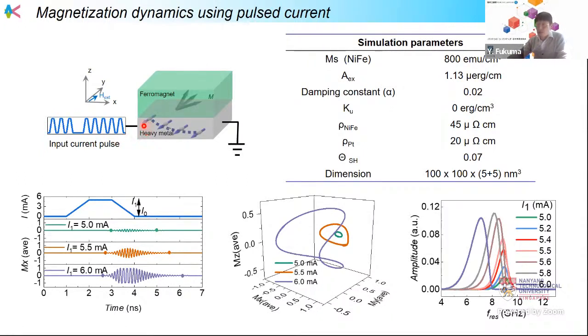For example, with spin orbit torque. These are the simulation parameters. And also we apply, for example, this kind of pulse scheme. Then instead of applying the pulse, we can inject the spin current into the ferromagnetic layer. Then, by the competition between the damping torque of the precession and the anti-damping torque from the spin orbit torque, it started the process like this.